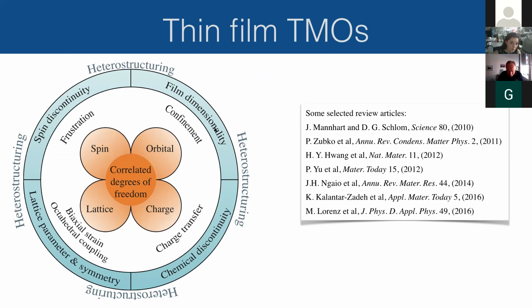So for example, if you make a film super, super thin, you will reach a confinement regime, which means that the out of plane orbitals will probably not be favored compared to the in-plane orbitals. And then this can, of course, couple to the other degrees of freedom, and you can get very cool physics out of this. So the other thing that I wanted this figure to show is that we are actually working in a field that is at the intersection of two fields that are already super rich, so heterostructuring and transition metal oxides. Now we're looking at heterostructures of transition metal oxides. So very many things happen.